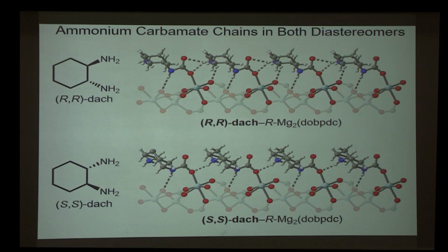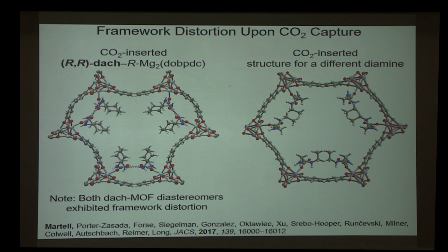The first observation is that in both diastereomers, chains of ammonium carbamate were observed in the long axis of the material, and this was not a surprise because other diamine variants had exhibited similar chains. What was surprising is that there was also an ion pairing interaction between chains of ammonium carbamate, and that's what I'm showing here. We had not observed this in other variants of the material, and what's quite interesting is that this interaction was enabled by the framework distorting its shape. Shown here is how the framework normally looks, where it's closer to a perfect hexagon. Here you can see it's pinching inward substantially, and this is enabled by the organic linker twisting and also bending slightly. So it's quite interesting that the MOF can change its shape to enable strong interactions between bound guest molecules.